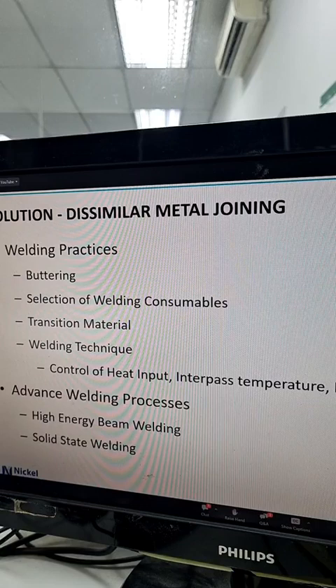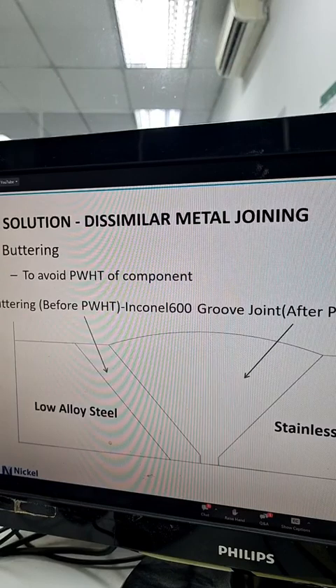The welding practices, like whether you are doing a buttering or not, how you are going to select your welding consumable, whether it is required to add a transition material similar to what we saw in the case of the steam generator. And also there are possibilities to use advanced welding processes like electron beam, and you have a lot of solid state welding processes. We saw this in detail. The best way is to produce with an Inconel buttering and a subsequent joint with Inconel.